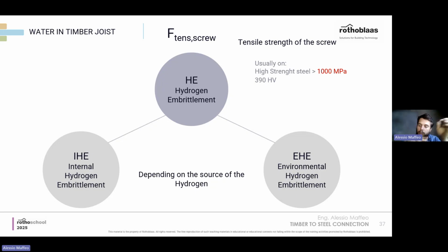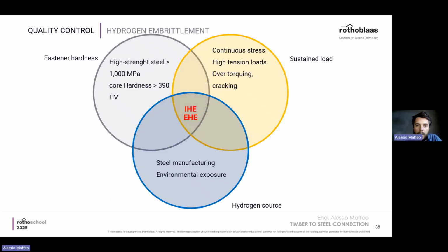These, together with all of the other factors that we just saw before, could mean that you could reach a failure due to the fastener breaking in a brittle way. It's a combination between all of the things that we just saw before, and could also be caused by one of these two hydrogen embrittlement failures. So again, everything, as I just said, is a combination of things.